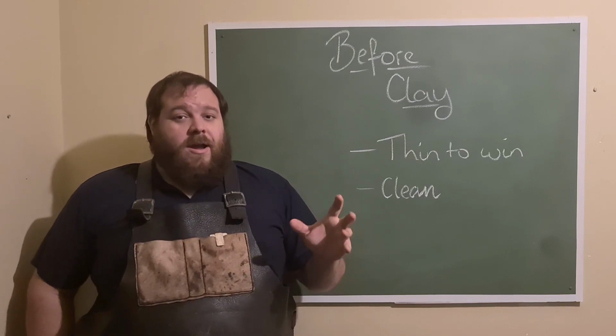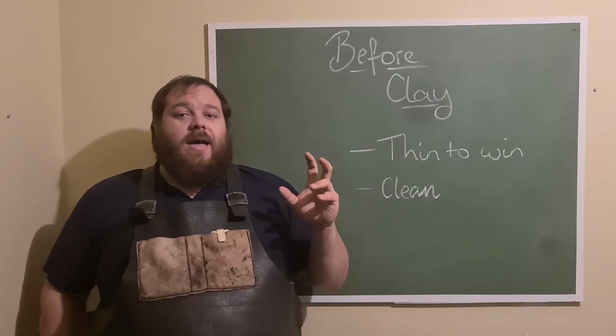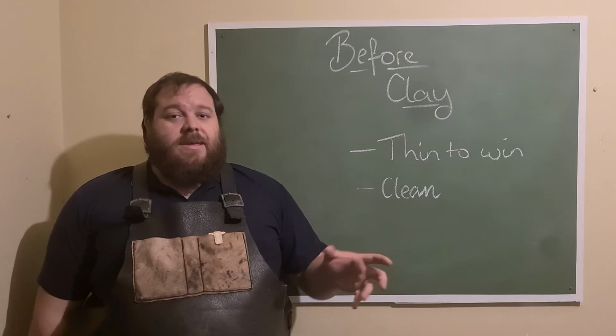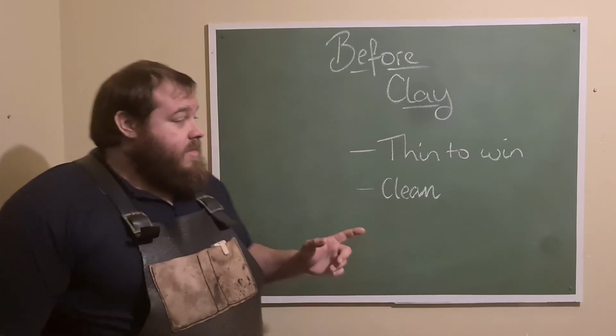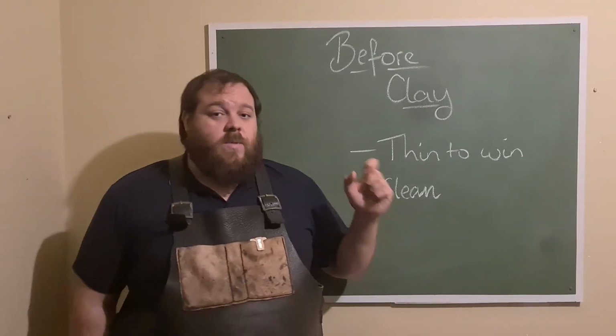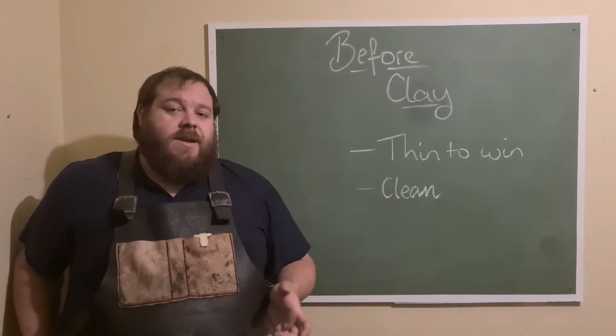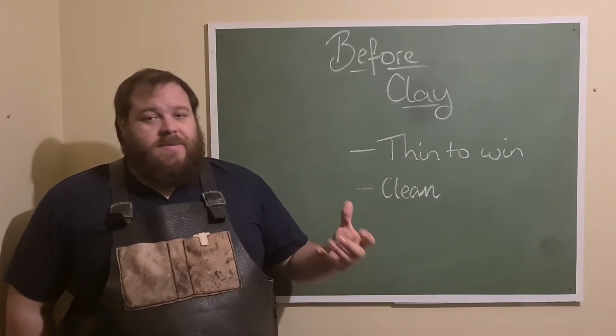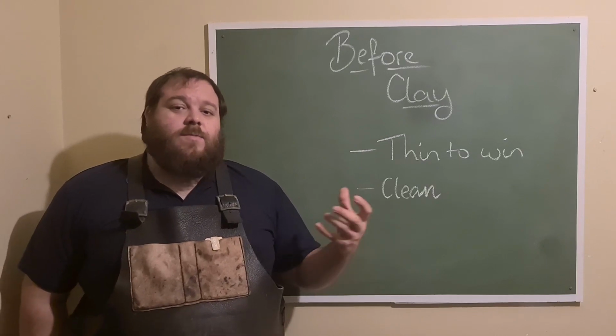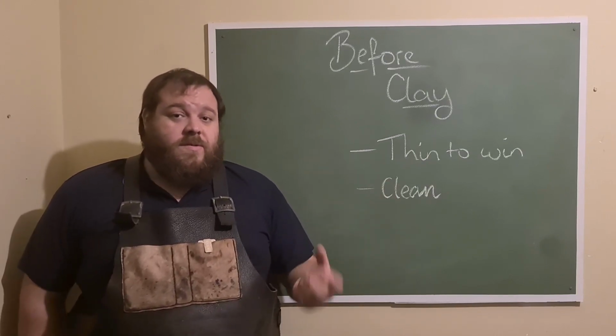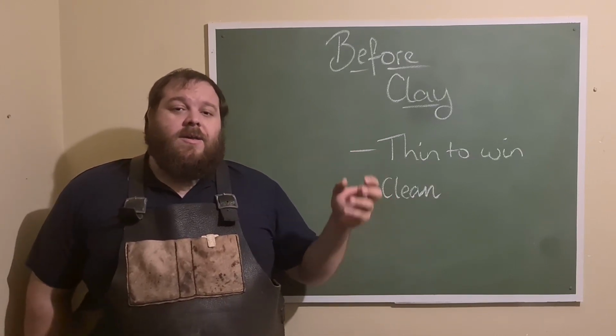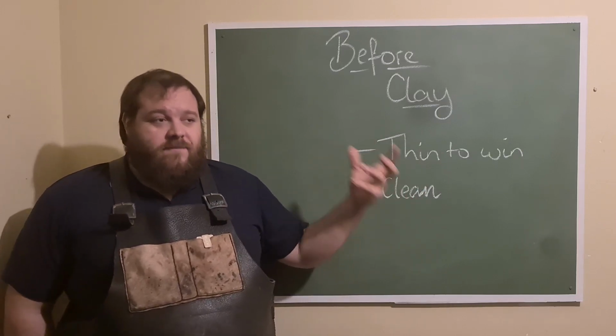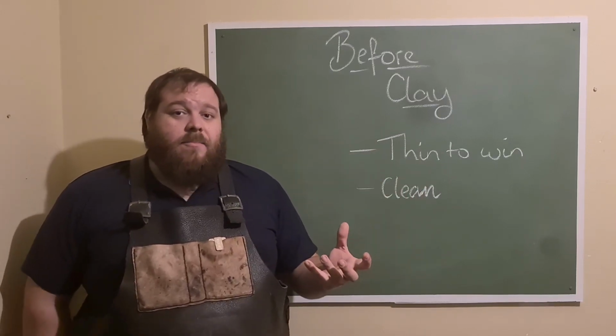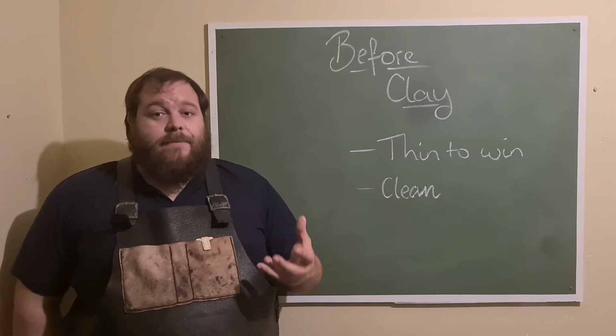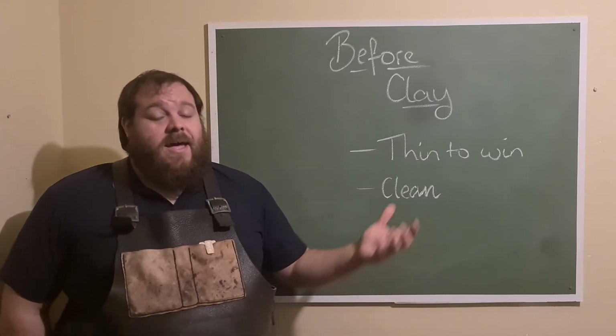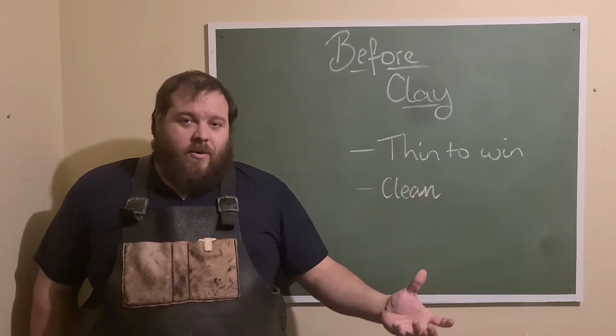And I normally pre-grind to 120 grit so that I have a nice clean surface to adhere to with the clay. The other thing is, the thinner your blade is when you go to heat treat, the more effective your clay will be. And this comes down to mass again. You're applying mass with the clay, and so therefore the thinner you are with your steel, the faster the areas that are going to harden effectively. So therefore they're going to capture that Hamon better than if they were thicker, because the thicker they are, the more mass they have, the more heat they have, the slower they quench.